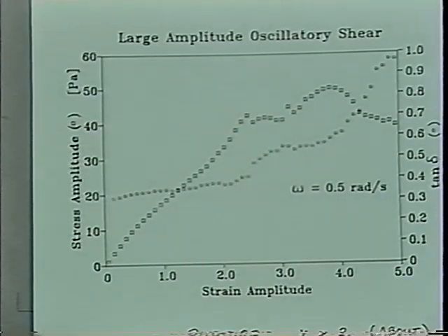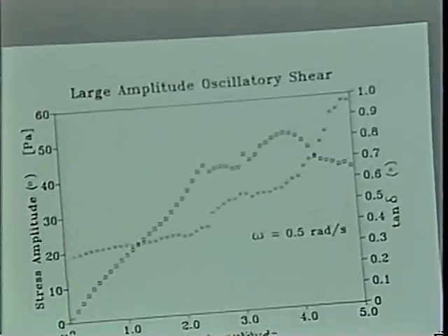So a strain of 2, which is very small. We would expect for a soft material like a gel a larger strain before breaking the material. But even that small strain is causing a rupture in that network structure.